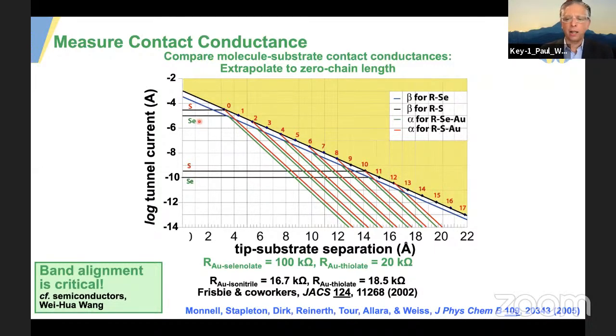And then we went back into the literature and we said, well, why did all those other groups get it wrong? And we realized that each group had calculated a different backbone. So it wasn't that selenium was 5 times worse than sulfur. It was just for the particular band alignment one got from that saturated, straight alkyl chain.